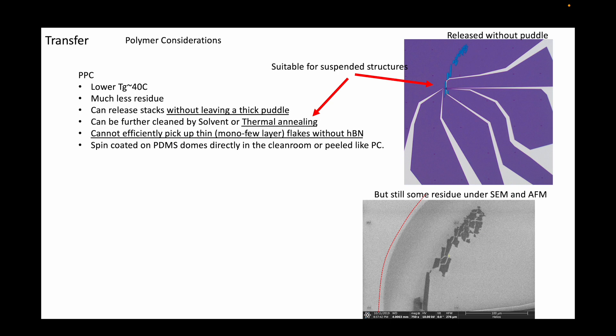Next, I am simply comparing the 2 most popular polymers used for pickup techniques which are PPC and PC. PPC has a lower glass transition of around 40 degrees Celsius and it has a relatively low adhesion, such that you can leave the flake down without leaving puddles of polymer residues.